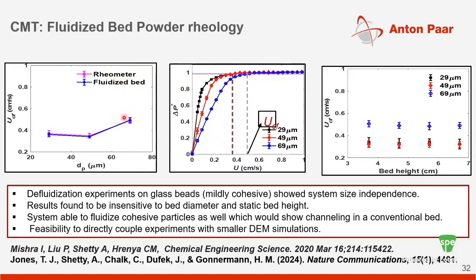We wanted to show that experiments done on traditional fluidized beds can be scaled down to the scale of a rheometer. If you monitor literature in this area, people have talked about how defluidization can be identified as a bulk measurement to extract interparticle cohesion between particles, using some sort of modeling approach. And what this work paved the way for is, since we can actually scale the system down to the scale of a rheometer, this also opens up the feasibility to couple with smaller scale DEM simulations, because now you can try to simulate what's happening at the scale of a rheometer.